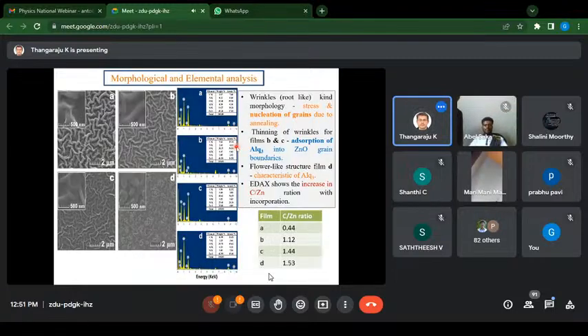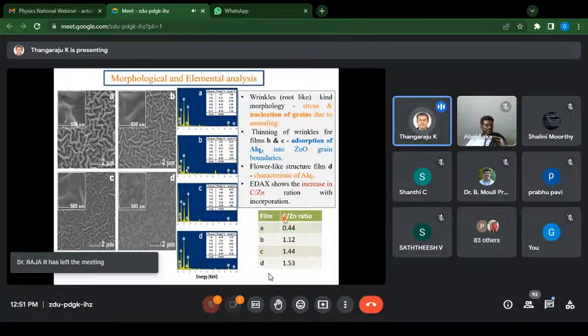You can see that the formation of the zinc oxide nanoparticles in the AlQ3 zinc oxide hybrid thin film is confirmed by scanning electron microscopy, and the presence of AlQ3 is also confirmed by calculating the carbon to zinc ratio, which gives the incorporation of the AlQ3 molecules in the hybrid thin films.